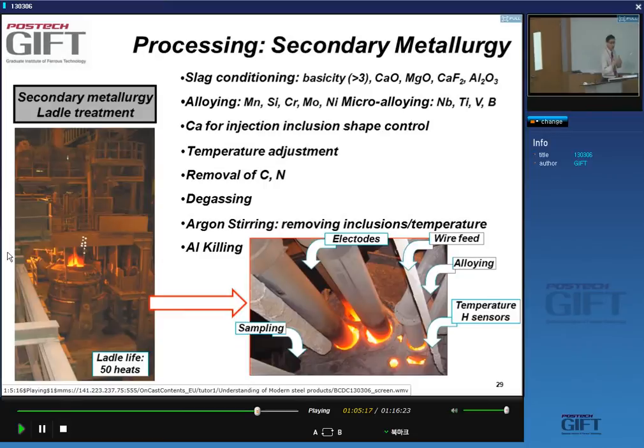And then you want to adjust the composition. 0.01% of carbon is very low. Maybe you need 0.1% of carbon. So you need to adjust this composition. All right? So let's have a look. The secondary metallurgy is very important because that's basically the moment where you set the composition of your steel. After that, you really can't change it anymore. So this is essential, very important.